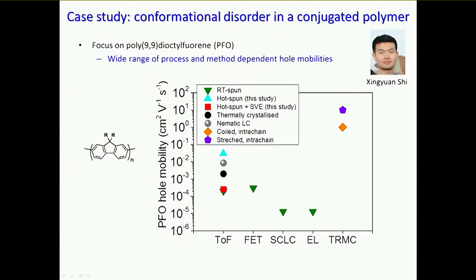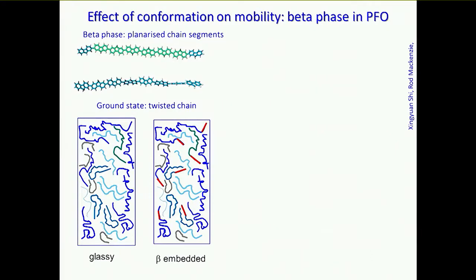So along the bottom, we have some different measurement techniques. And even with a single measurement technique, you may find reports of mobilities that vary by orders of magnitude. So it's really quite a complicated problem. We can't easily start with that chemical structure and then explain why you can have almost any number you like for the hole mobility. So what we decided to do was to try to look at this and see, could we control the conformation of the conjugated polymer to try to make sense out of it?